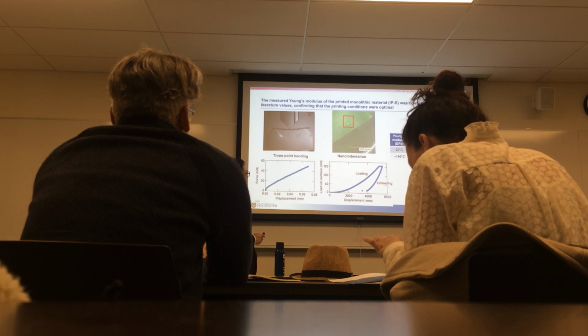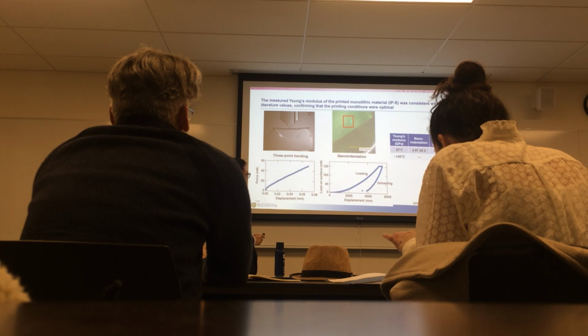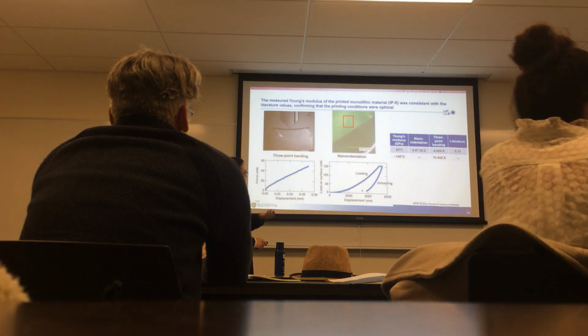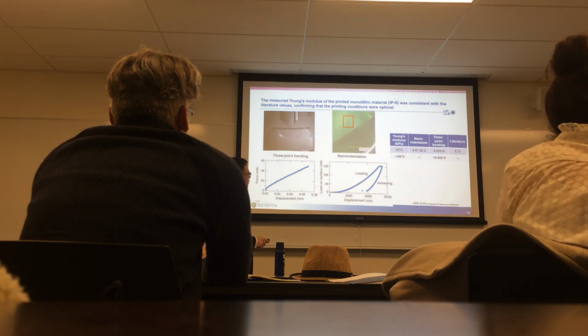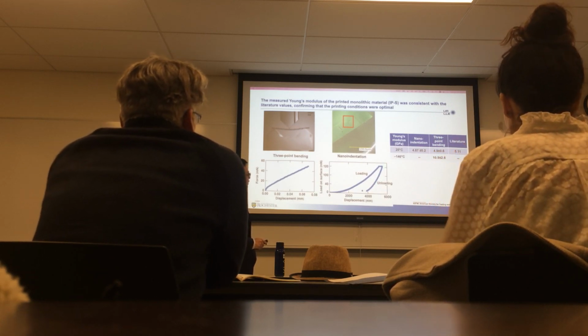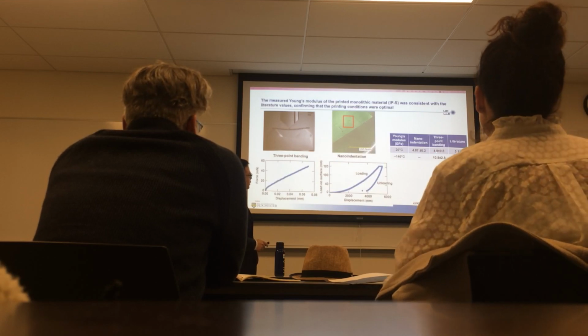For nano-indentation, a tip compresses on the material surface. There are two parts: one is the loading force part, and the other is the unloading force part. Depending on the unloading force process, the equipment calculates the nano-indentation result. From these two methods, we find the results are quite similar to our literature results.